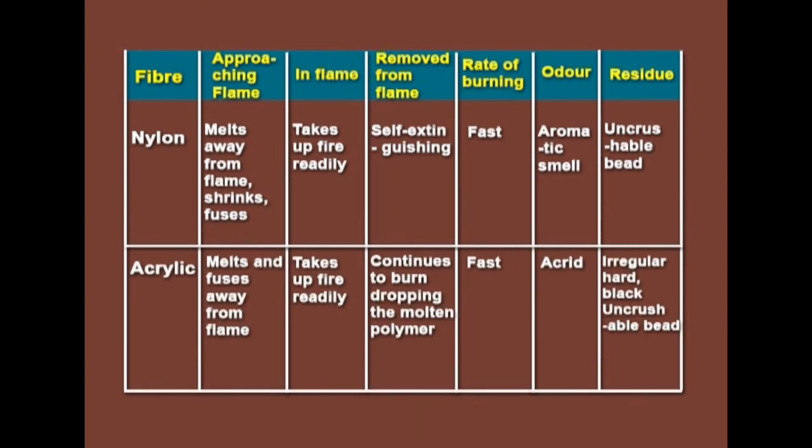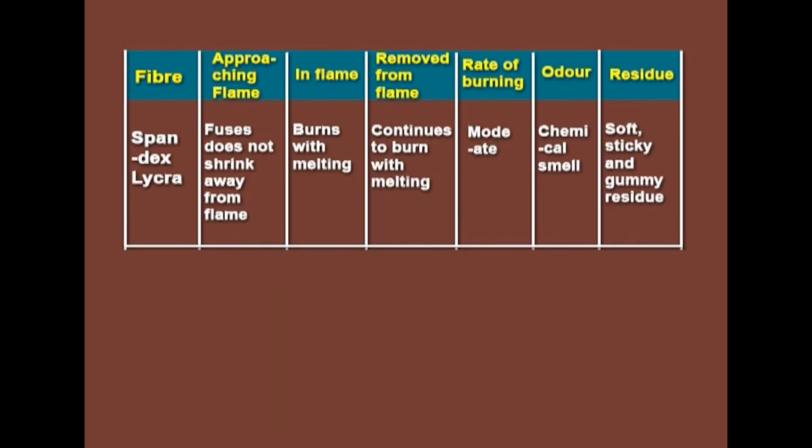And the other synthetic fiber is the acrylic, which looks like wool. While approaching the flame, it melts and fuses away from the flame, and it takes up the fire readily in flame, and it continues to burn, dropping the molten polymer off once you remove the fiber from the flame, and the rate of burning is going to be fast and gives an acrid smell, and it gives an irregular hard black uncrushable bead. And we have lycra, which is also used today in most of the fabrics, stretchable fabrics.